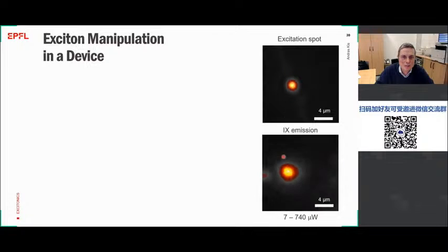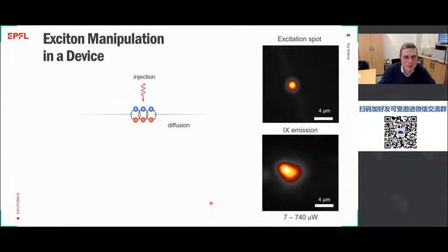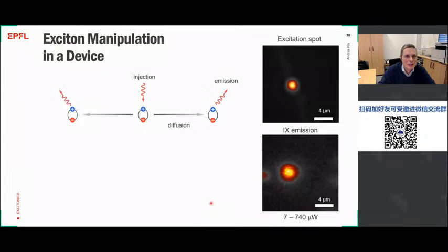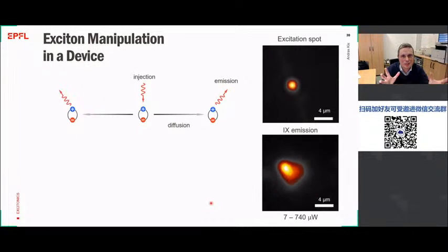So here the spot is shining on the heterostructure at the corner, and then you get this spreading of the emission. It's normalized in intensity, but you see that the cloud is sort of spreading out from the point at which we inject the excitons. So why is this happening? What's happening is that we inject excitons under the laser beam. They can diffuse a certain distance away from the injection point, and once their lifetime is reached, they emit light.